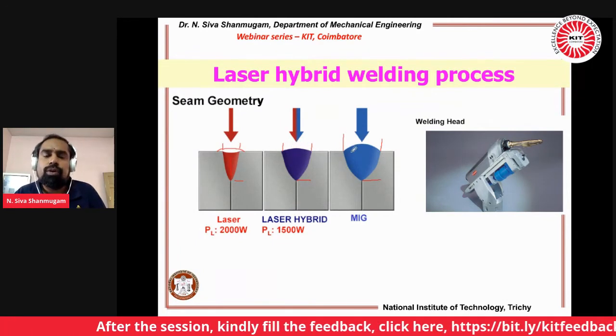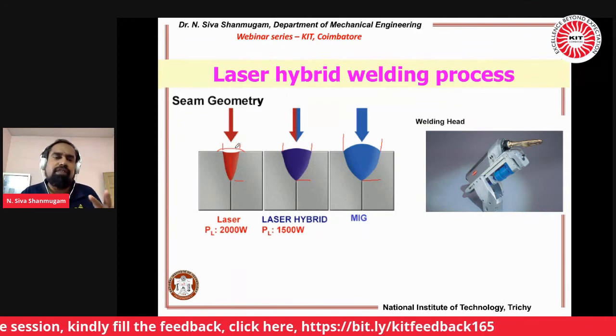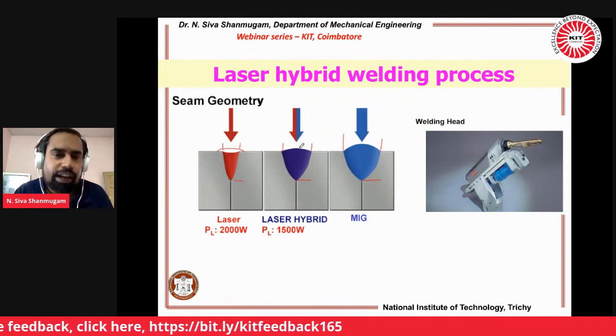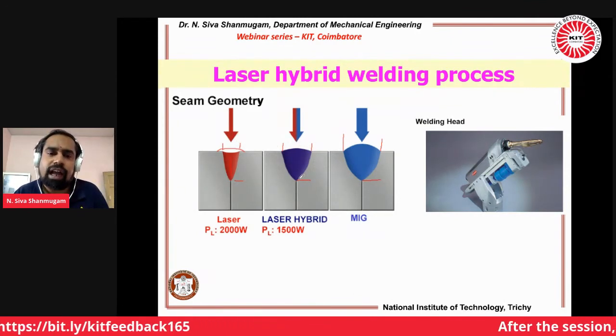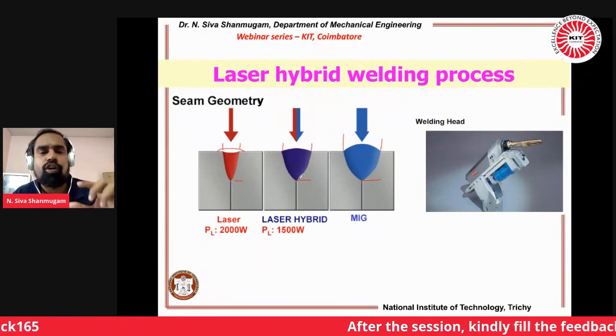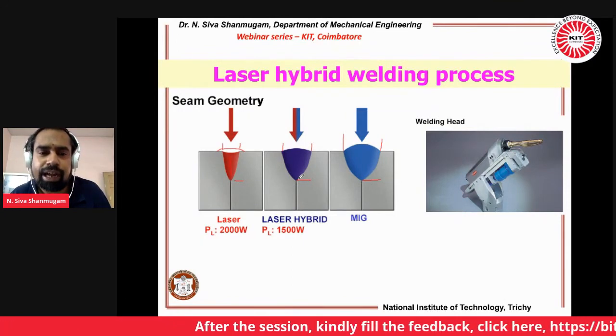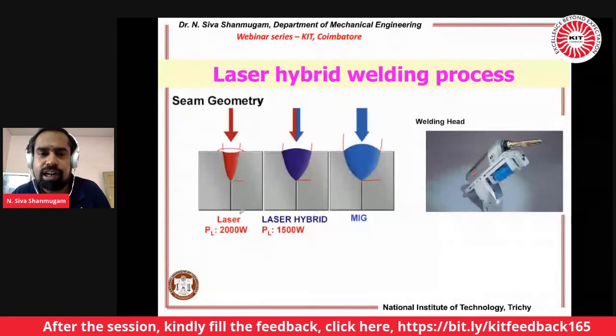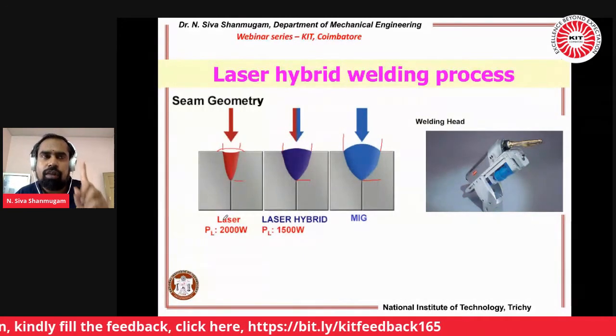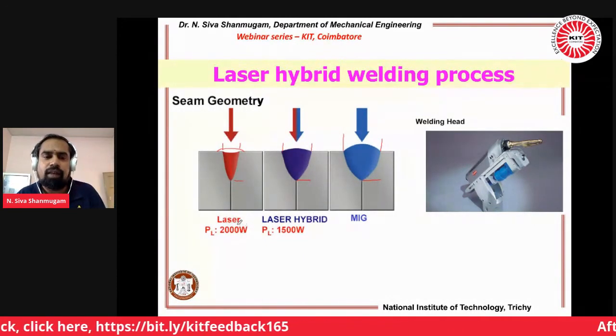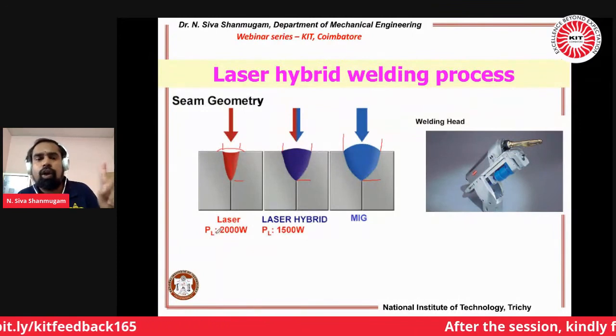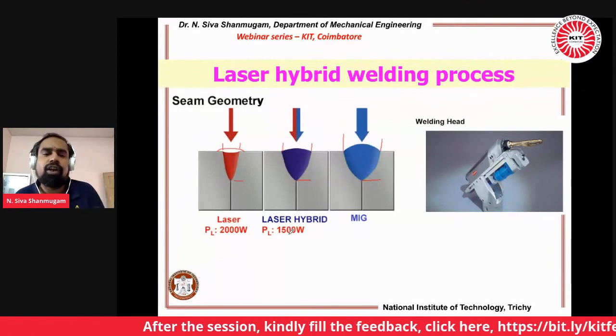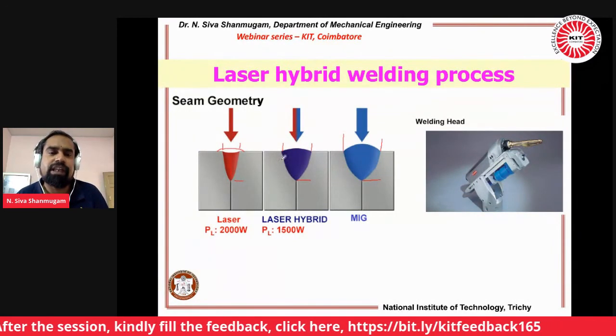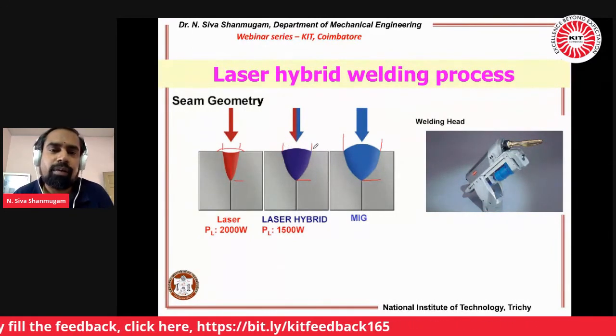So when you use the MIG in combination with the laser, you can get a reinforcement, and also you can achieve a good depth of penetration. That is the beauty behind the laser hybrid welding. Normally, when you operate only with the laser, the power is around 2 kilowatt. But here it is not 2 kilowatt. Within 1.5 kilowatt, you can achieve the penetration as well as a good bead width.